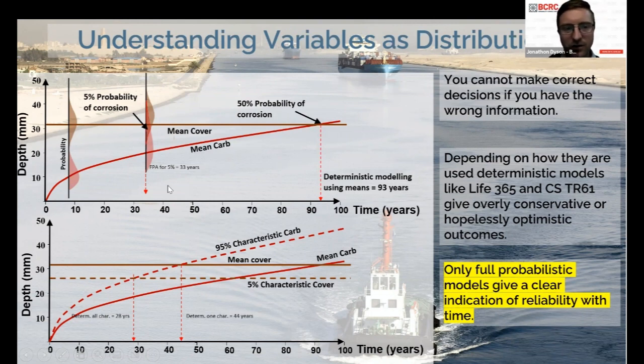But if you did full probabilistic analysis where you treated everything as a variable, you can see that carbonation is not always the same. Carbonation in one spot of the structure is, for example, 20 millimeters, in another spot it might be 14 millimeters, in another 23 millimeters. So it's a distribution, and so is the concrete cover. If you treat them that way and use characteristic values, the upper 5% carbonation depth and the lower 5% concrete cover, and do full probabilistic analysis for those 5% values, you actually get a remaining service life of only 33 years, compared to 93 years doing deterministic modeling using mean values. That's a big difference.